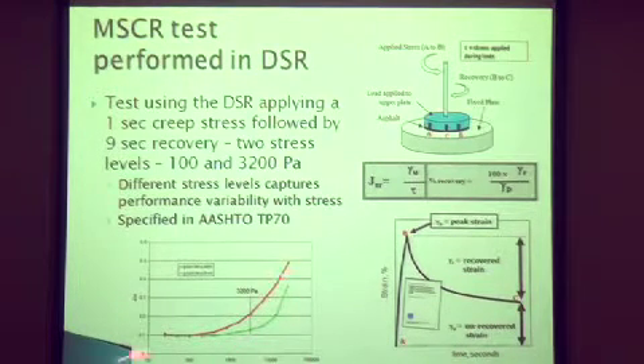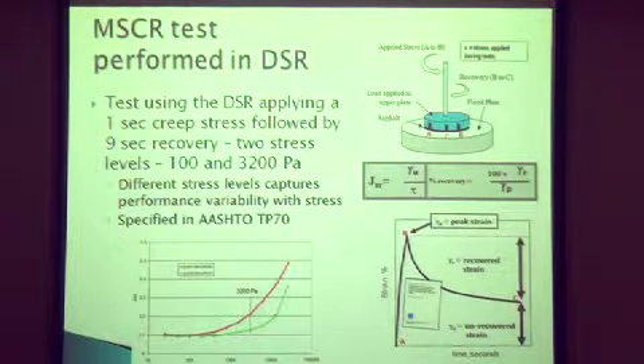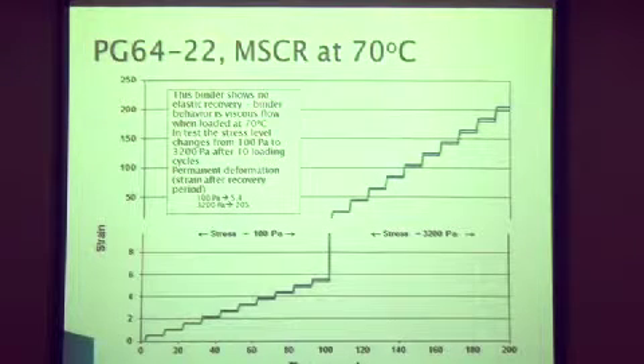So Ron, when he was doing his research work, tried a whole bunch of different stress levels, and to make a specification test you normally have to have some sort of compromise. The compromise was that this 3,200 stress level was reasonably close to what would be expected in the pavement asphalt binder film to undergo, and reasonably good at distinguishing between the different material types. So this is what went into the stress level. One gives us a very similar number, performance we would get with the old specification, and one which would really enable us to distinguish between the good performing binders and the poor performing binders.